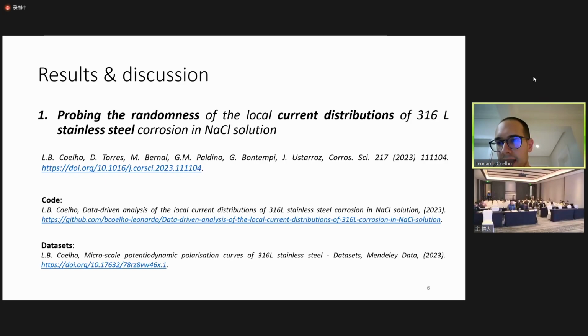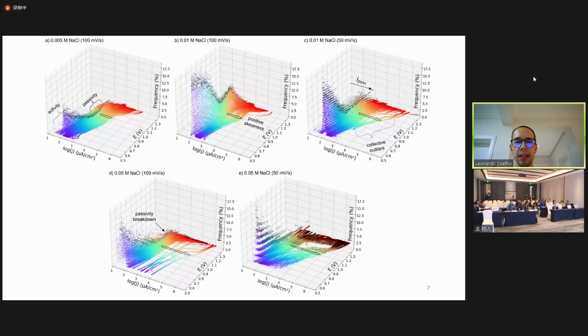So let's start with the first study, which is called Probing the Randomness of the Local Current Distributions of 316L, which is a stainless steel, a classic one, Corrosion in sodium chloride solution. Related codes and data sets can be accessed as described in these details. And as I mentioned, we employ different combinations of aggressiveness, if you will. On the top left, we have the least aggressive condition, and on the bottom right, the most aggressive condition.